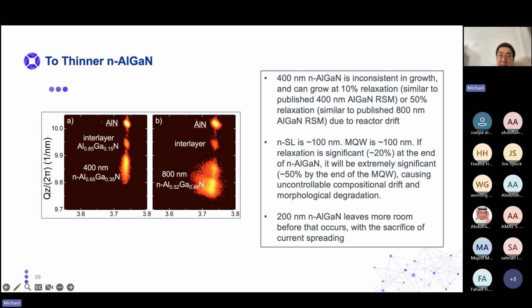And if the relaxation is significant, that shows that we're drifting towards that uncontrollable compositional drift and morphological degradation, and also cracking. Since our n-type smoothing layer is about 100 nanometers and our quantum wells are about 100 nanometers, if the relaxation is already significant at the end of the n-type aluminum gallium nitride, then at the end of the quantum wells, it will be catastrophic.